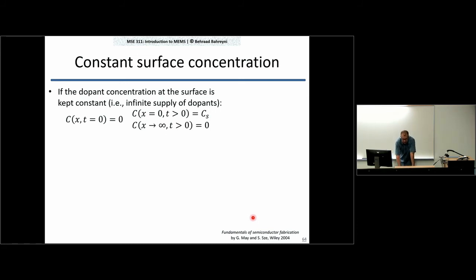So under these conditions, these assumptions, well, the concentration at the beginning of the process is 0. There is really nothing that is inside my silicon substrate at the beginning. So C of x, t, where x is the distance from the substrate, at t equals 0 is 0. And then as the process goes on, C of 0, t, meaning the surface, at any time is constant. I keep it at Cs, some fixed concentration. So the surface concentration is constant.